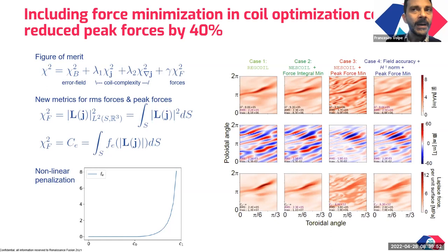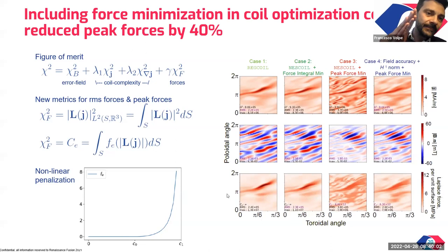The other issue, which is the one that prompted this work on the force minimization, is that now you have the superconducting film tightly bound on the metallic substrate, so they move together, but they move together under the effect of very strong forces. So your structural material is being subject to these huge J cross B forces. And basically, the material is subject to the hoop force, and is subject to other deformations, and the cylindrical surface is trying to deform under the effect of these forces. You can prevent such deformation by adopting a thick enough metal substrate, but for cost reduction, we prefer to be more elegant and reduce the forces and therefore the required thickness of the substrate for the same amount of desired deformation or tolerable deformation.